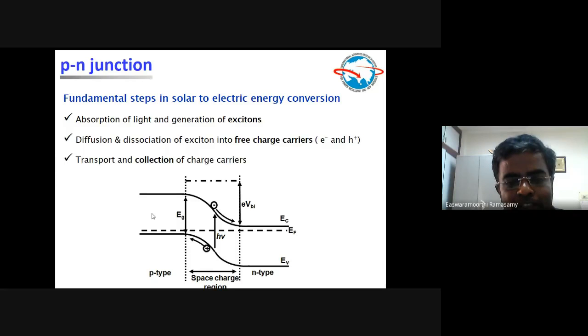Once light hits, with photons interacting with this material with energy greater than the band gap, an electron and hole pair can be created. We call it an exciton. So absorption of light is the first step, and then the exciton forms. It dissociates at the interface to become free charge carriers. The electron and hole become separated, and the electron goes in this direction and the holes follow their own preferred direction.